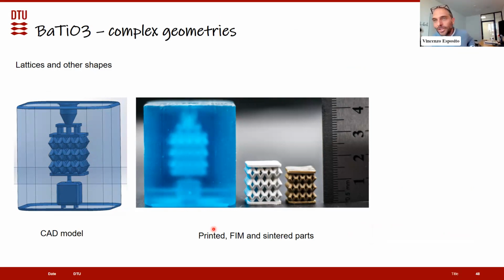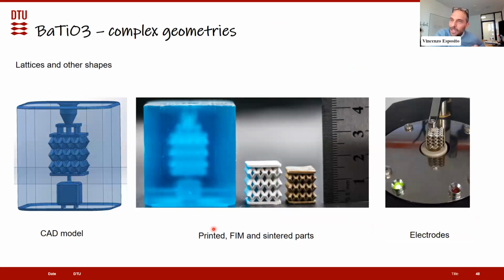But the awful truth is that when you want to test these materials, for example for electromechanical actuation, where you want to see what happens when you apply electric fields, you are in a very uncomfortable position where you don't know where to put electrodes and which kind of electric field to apply, because they are so resistive that it is really impossible to go through. So if you have an electrode-free application in mind, these lattices are interesting. If you don't have this option, it gets a little bit complicated to place electrodes in the right place.